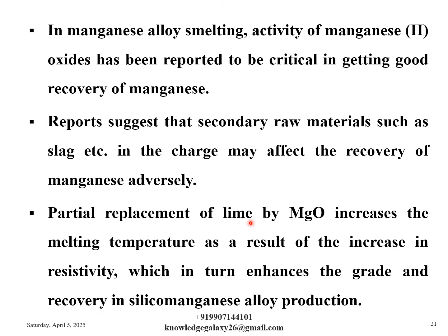Partial replacement of lime by MgO increases the melting temperature as a result of the increase in resistivity, which in turn enhances the grade and recovery in silicomanganese alloy production. My dear friends, this is the main reason why to use dolomite, which is a double oxide of CaO and MgO, as a flux in place of lime. So this is a very useful point. Please do remember this.